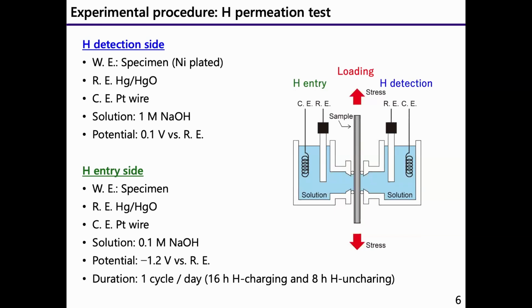The reference and counter electrodes were same as hydrogen detection side. The cell was filled with 0.1 molar sodium hydroxide aqueous solution. The specimen was polarized at -1.2 volt for hydrogen charging. The duration of this hydrogen permeation test was 1 cycle per day with 16-hour hydrogen charging and 8-hour hydrogen uncharging. The hydrogen permeation test was repeated several times with various stress and strain conditions.